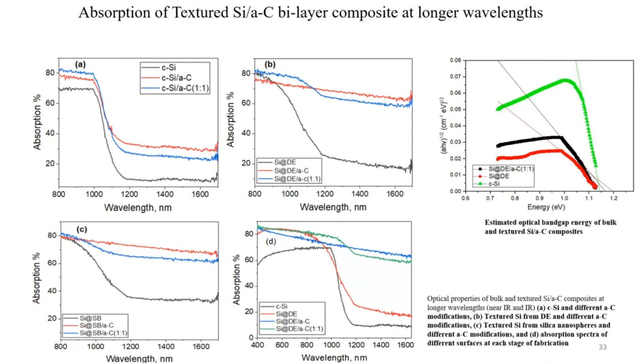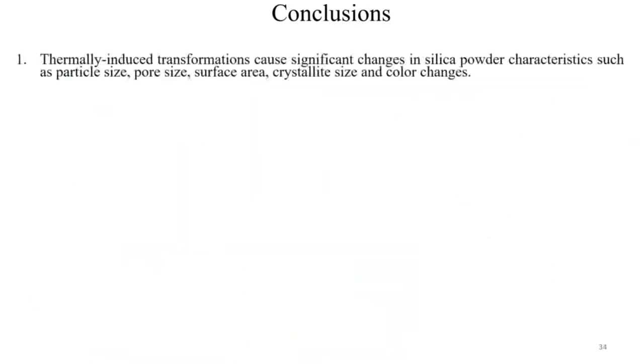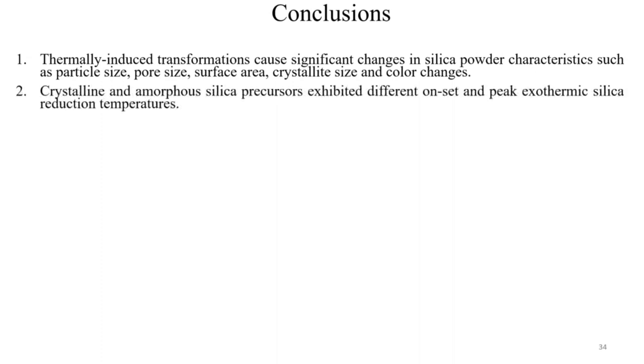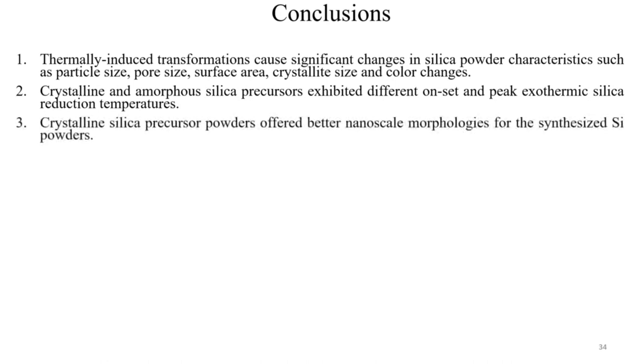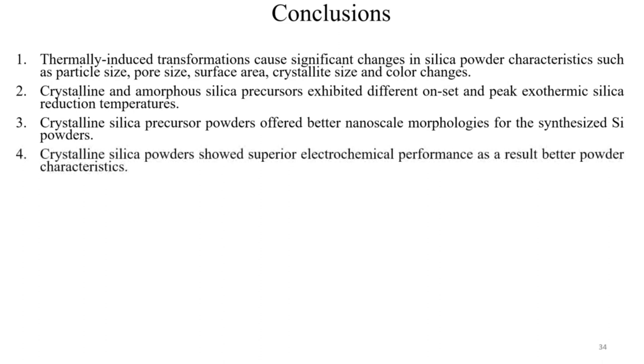of silica. So in conclusion, thermally induced phase transformations caused significant changes in the powder characteristics, such as the particle size, pore size, surface area and crystallite size, and also color changes. And crystalline and amorphous silica precursors exhibited different onset and peak exothermic reduction temperatures. The crystalline silica precursors offered better nanoscale morphologies for the synthesized silicon powders,